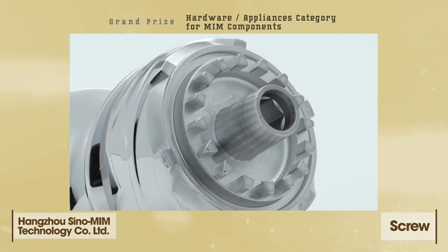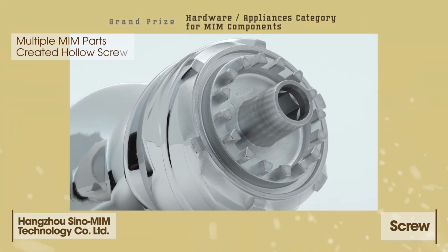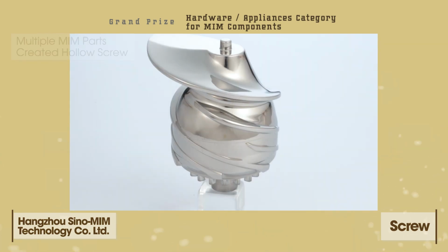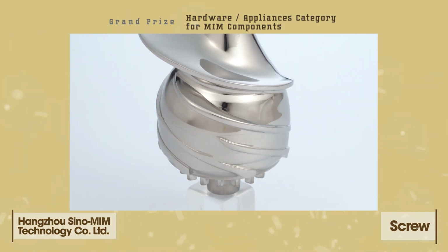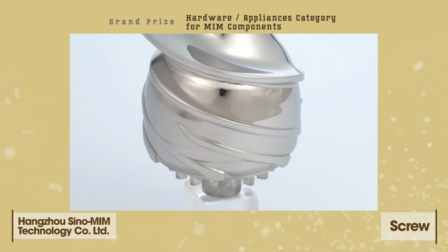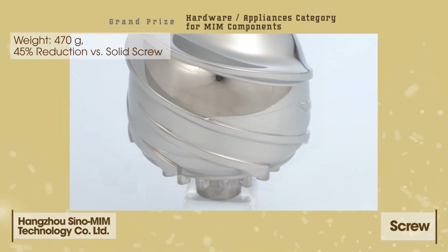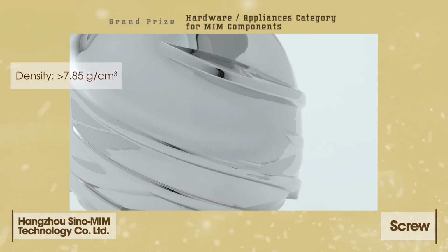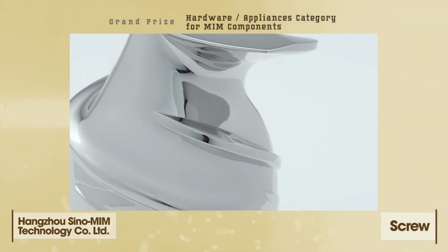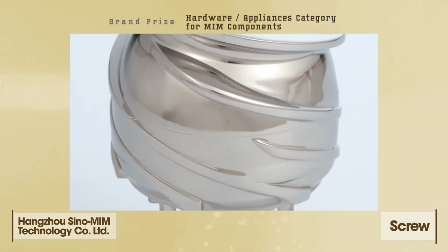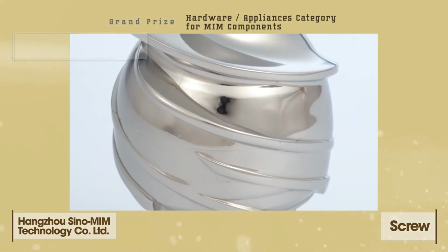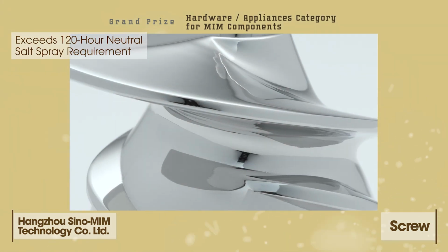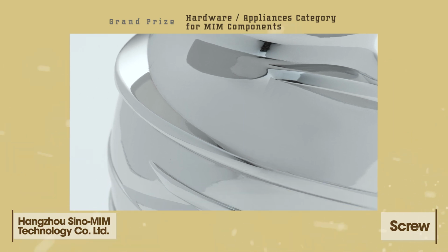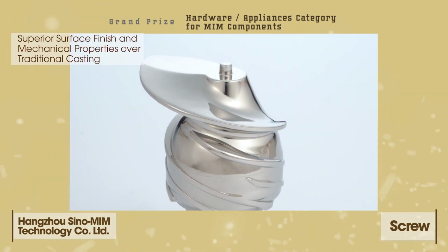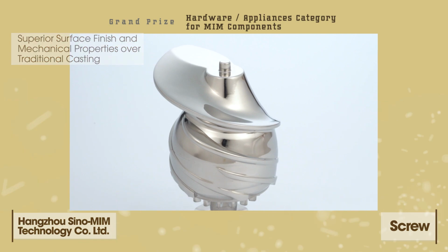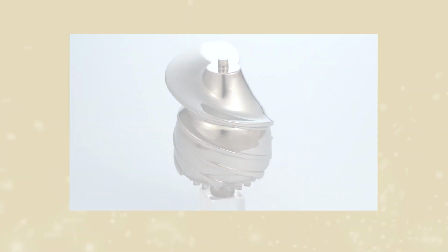A solid metal iteration of the design weighed nearly 860 grams, which was not ideal. The screw was redesigned, divided into several small parts, and the hollow interior structure reduced the part mass to 470 grams, a 45% reduction. The sintered density of the parts is greater than 7.85 grams per cubic centimeter, and the screw can survive a neutral salt spray test of 120 hours. The conversion from plastic to MIM has led to a better surface finish and mechanical properties, and a significant improvement in the lifetime of the product.